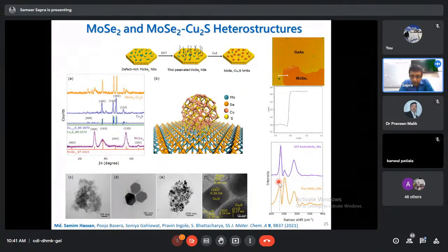And this is something we can also verify by doing some Raman spectroscopy. If you look at this peak, that's the A1g, and here you have the E2g, so the out-of-plane and the in-plane modes that are exhibited. And this is for pure molybdenum selenide, and that's for DDT. They don't change much. Of course, there's a change in the frequency, and that is because when you have DDT, some of the bonds get affected. I'll not discuss that. The more important thing is this mode that comes in between. That is because of the presence of defects.